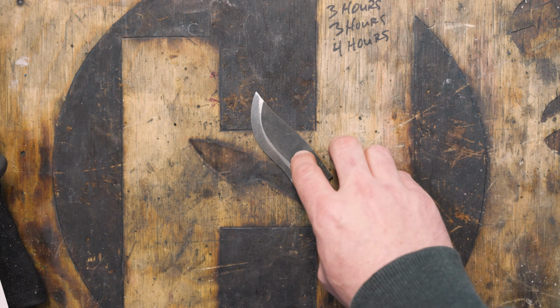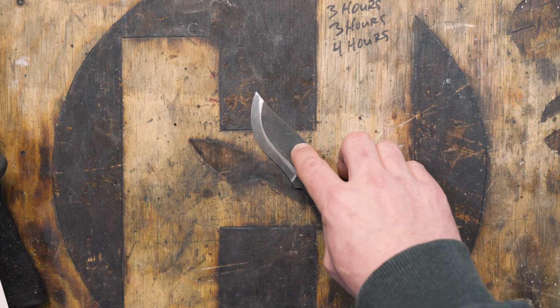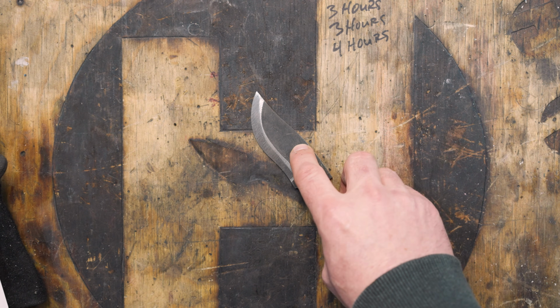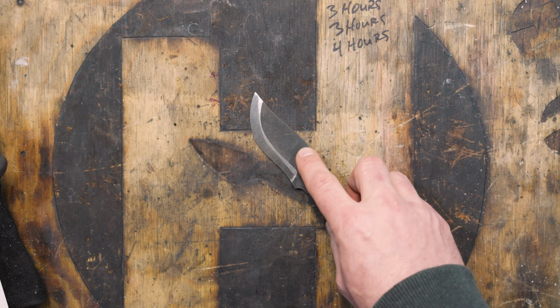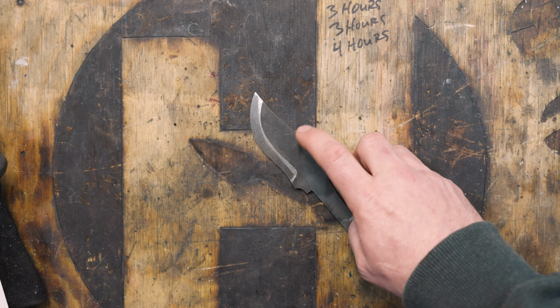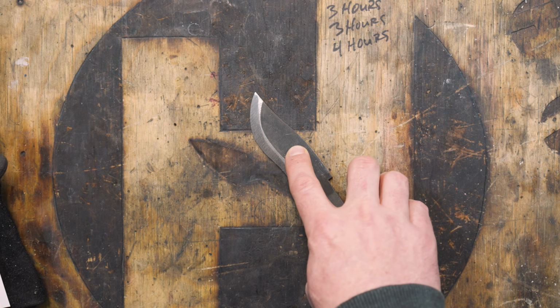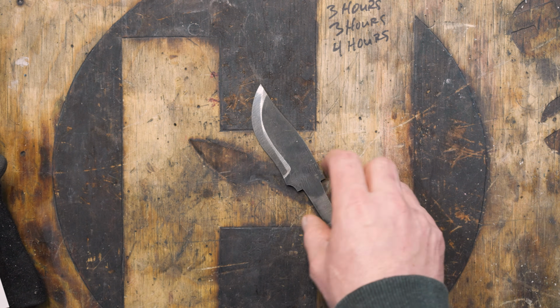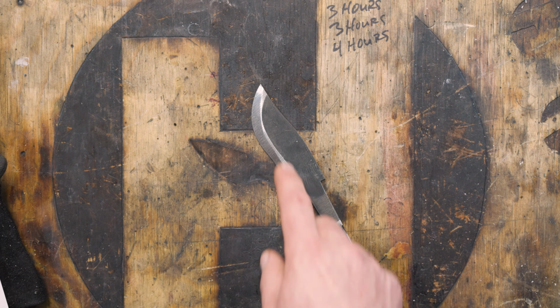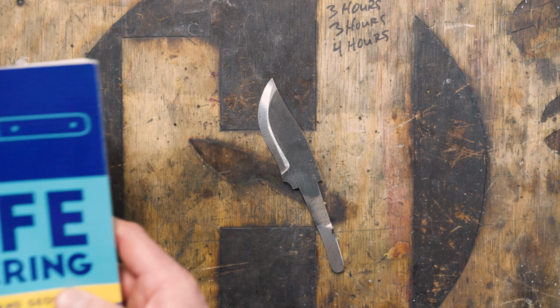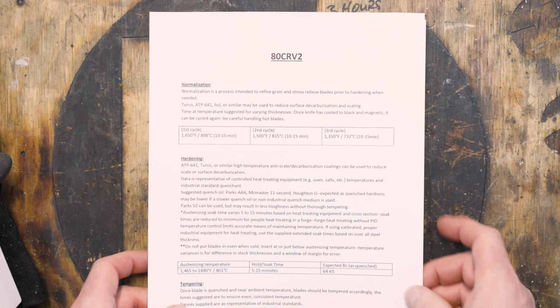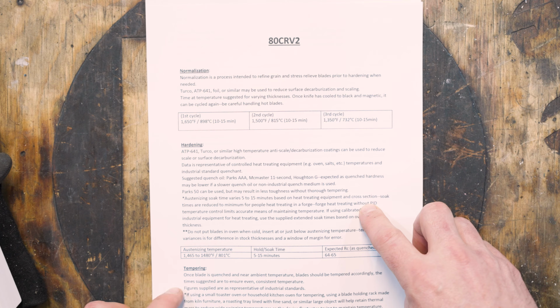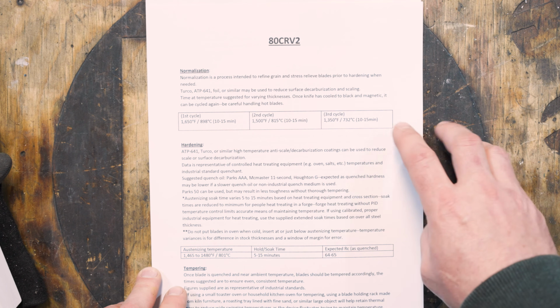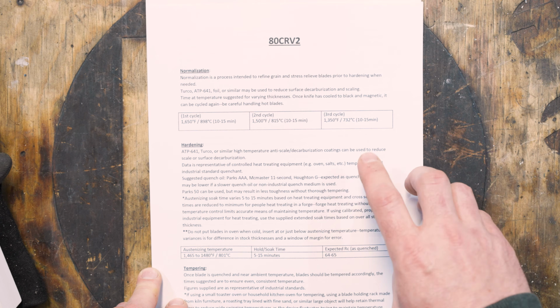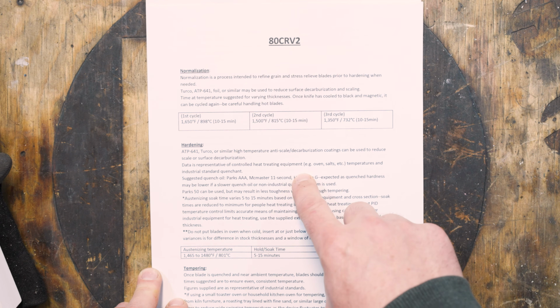The only difference is that 80CrV2 requires a soak, whereas 1084 you can basically just get up to temperature and then quench it right away. The 80CrV2 requires like, I don't know, a 10-15 minute soak. I mean, it doesn't require it, but if you want to get the most out of it and ensure that it's hardened, that's the way to do it. Anywhere you buy your steel, they're pretty much going to have a little chart like this that tells you how to heat treat their steels. And this is from the New Jersey Steel Baron.